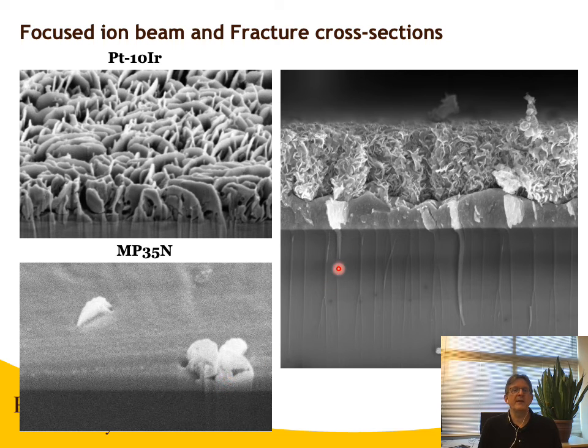But we went ahead and we made a fractured cross-section of a material that was on a witness sample on sapphire. So down here we have the sapphire substrate. Here is the iridium oxide layer that forms before you start forming the platelets. And then this is the high density of platelets on the surface that occurs at the high oxygen partial pressures. So all of these materials show some evidence that there's a continuous layer of iridium oxide that forms before you start getting the platelets, that the platelets do not nucleate directly on the substrates.